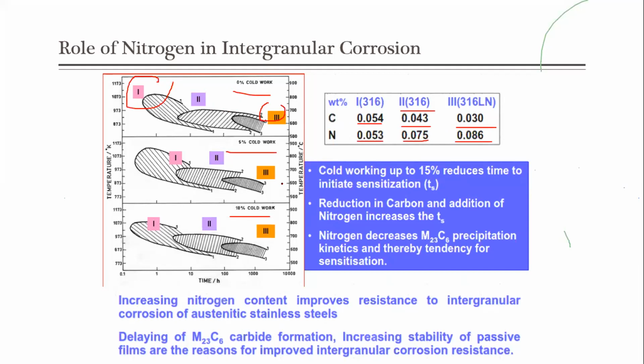And they have studied the time transformation curves for 0% cold work, 5% cold work, and 10% cold work. And they found that cold working up to 15% reduces the time to initiate sensitization. Hence, you can cold work the ASS sample, which in turn reduces the time to initiate the sensitization. And reduction in carbon and addition of nitrogen increases the transformation time. If you increase the nitrogen content and reduce the carbon content, then you can increase the transformation time.